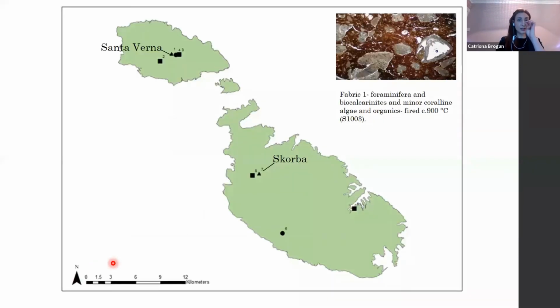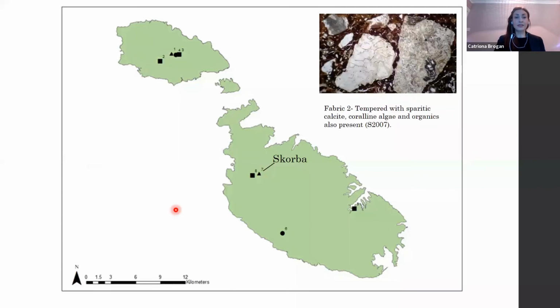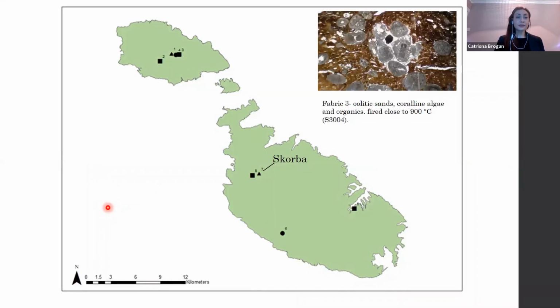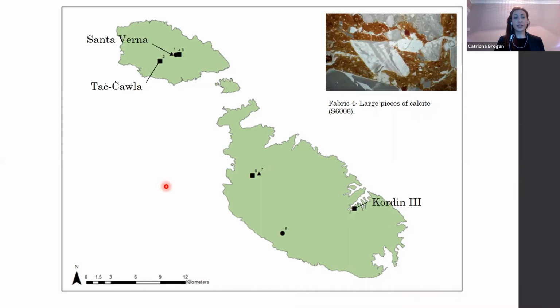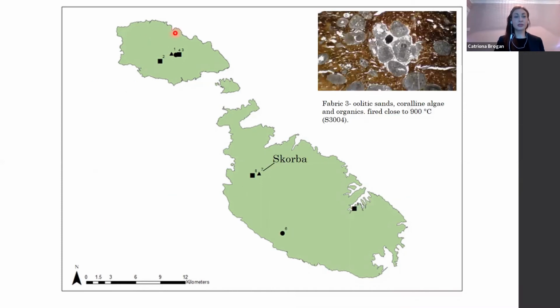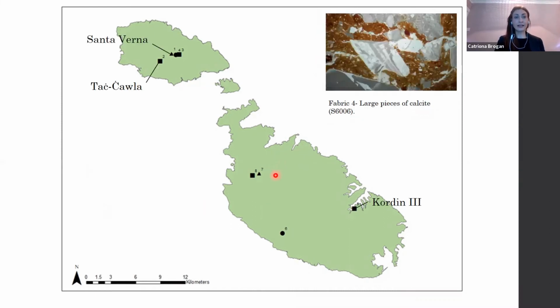And then its occurrence across the islands. Fabric 1 we find on sites from both islands, whereas fabrics 2 and 3 we've only found evidence of so far on Malta. And finally the coarseware has shown up at Santa Verna, Tac-Cawla and Kordin 3, so we know that it's on both islands.